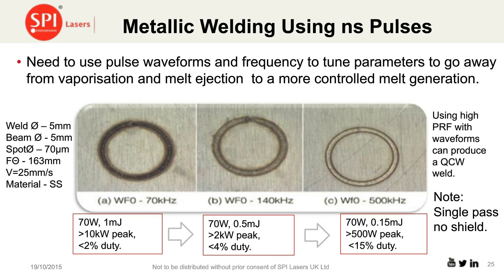So, moving now on to welding of metallic materials using nanosecond pulses. As we've always said, we need to use the pulse waveforms and frequencies to tune the parameters, to move away from what I would call vaporization and melt ejection, to basically create an environment where you're actually generating a controlled melt. And this is an interesting set of pictures, because going from left to right,